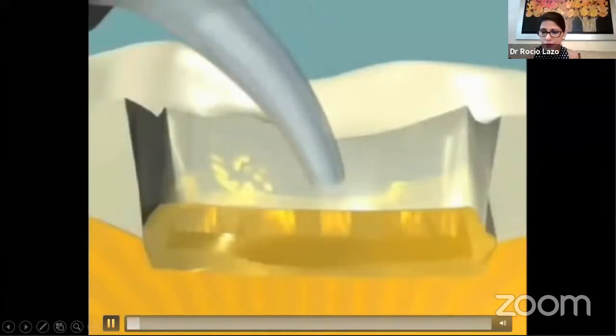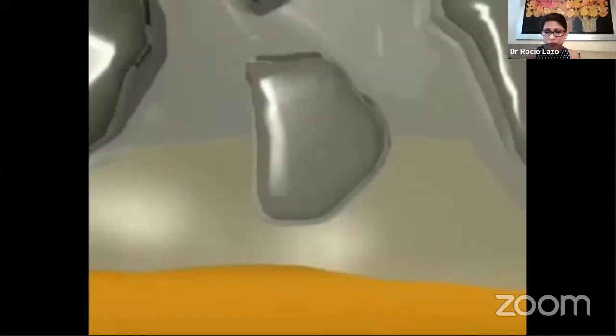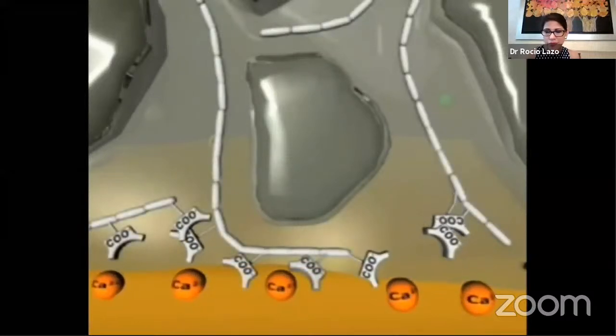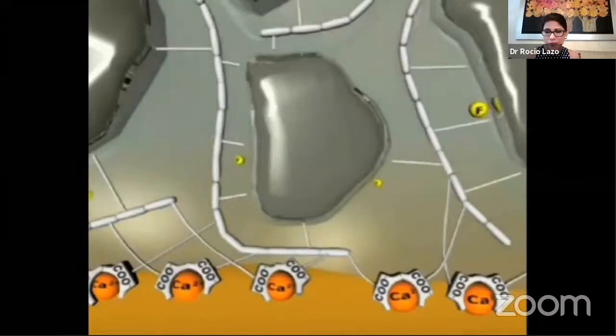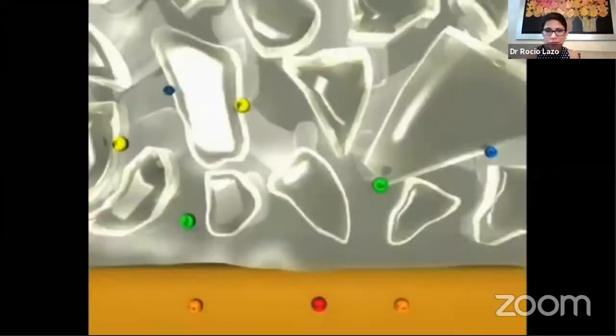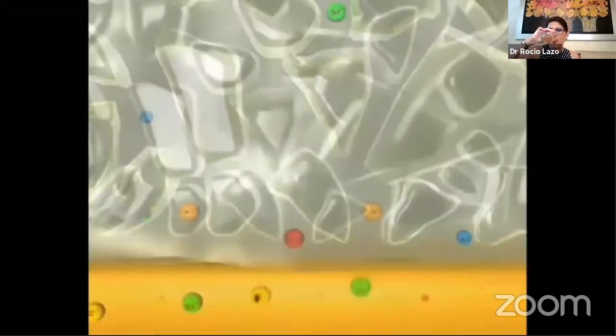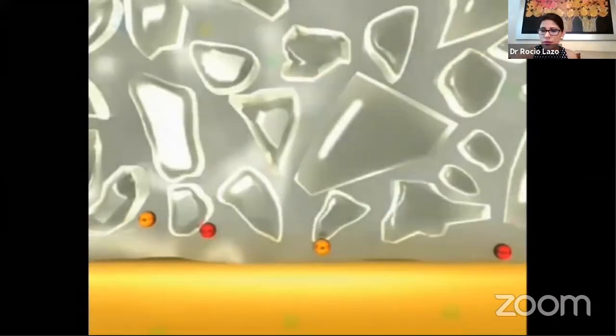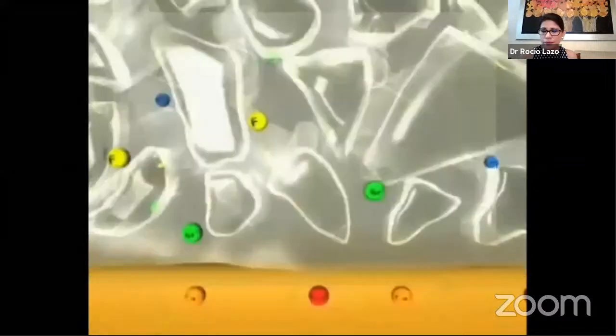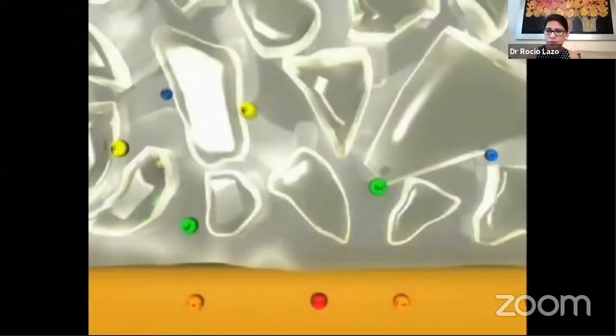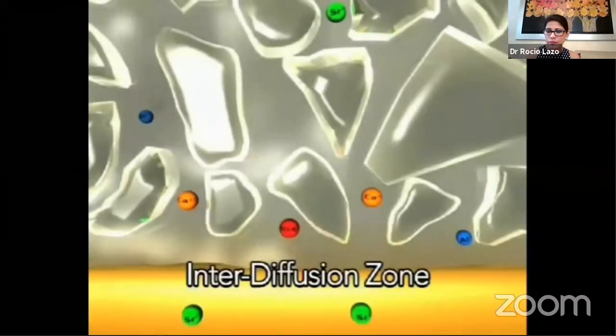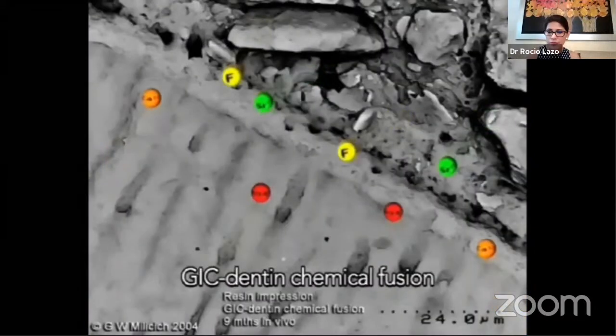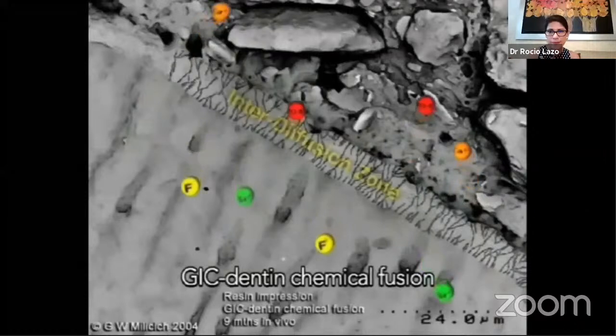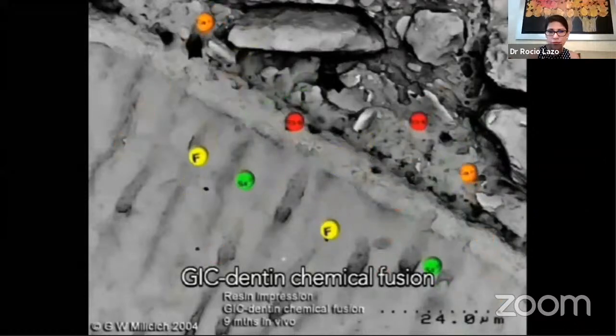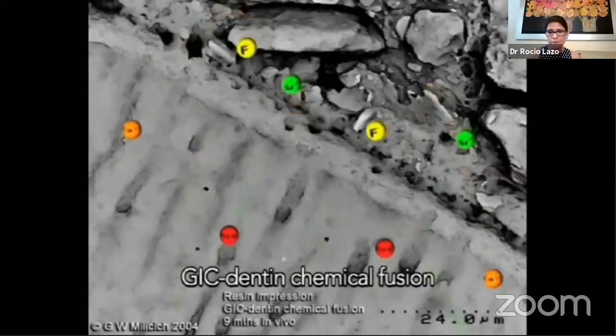It is essential that the glass ionomer is placed while it has a glossy surface. The gloss is free polyacid, which is able to penetrate the cavity surfaces to form a strong, hydrolytically stable chemical bond to calcium ions within the dentin and enamel. In addition to chemical adhesion to calcium in the tooth, a fusion bonding process takes place as well. Calcium and phosphate ions from the polyacid-treated dentin and enamel, and strontium and fluoride ions from the unset glass ionomer intermix and precipitate, forming an interface called the interdiffusion zone. This zone is stronger and more acid resistant than either the glass ionomer or the tooth. The combination of the interdiffusion zone and the chemical bonding provides the basis for a strong, stable adhesive interface and creates a bacteria-proof seal for the cavity, best described as a chemically fused seal.